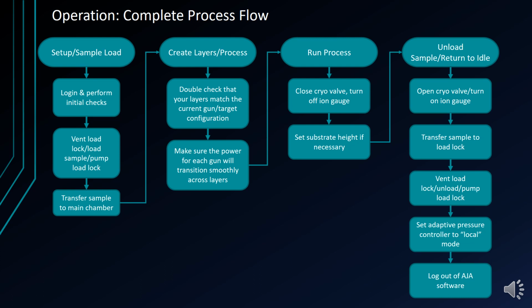Next, we will create our layers and processes. Practically, though, you can do this at any time. On top of programming the desired layers, this involves double checking that your layers match the current gun and target configuration, as the target configuration can change as different materials are loaded by request. Make sure that the power will transition smoothly across layers. Watch out for accidental sudden changes, and be sure you are not going to exceed a target's maximum power.